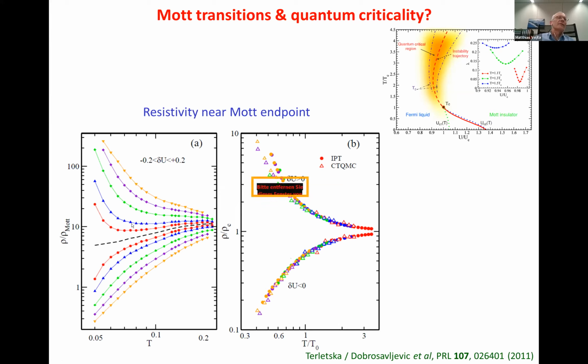And again, that is the resistivity. In these data, you see trajectories which look metallic, on the left-hand side of the red line, which go down to the metallic Fermi liquid—these are the resistivity trajectories down here, the lower part of the phase diagram. And you see others which are insulating, on the right-hand side of the instability trajectory.